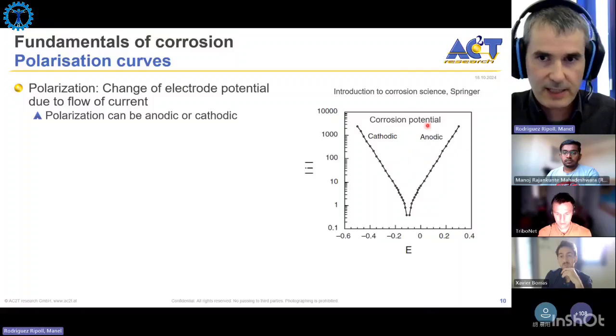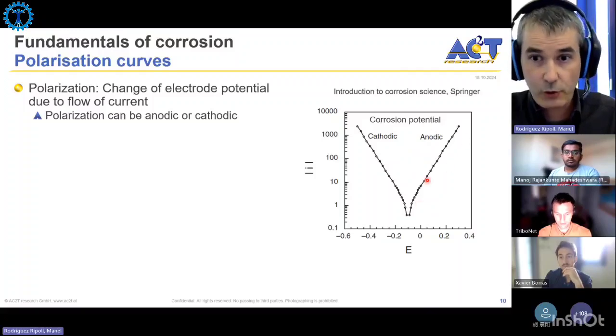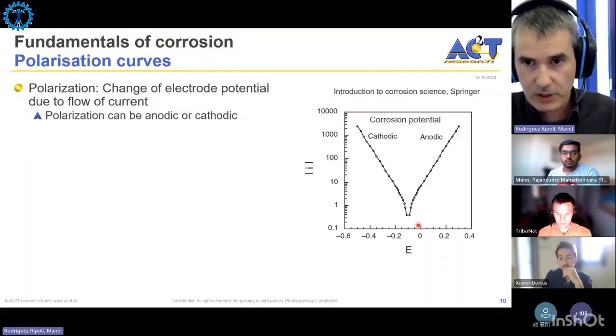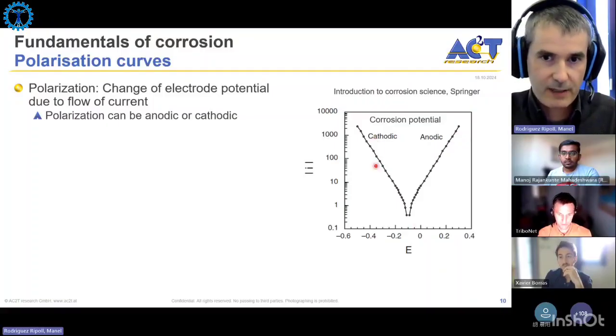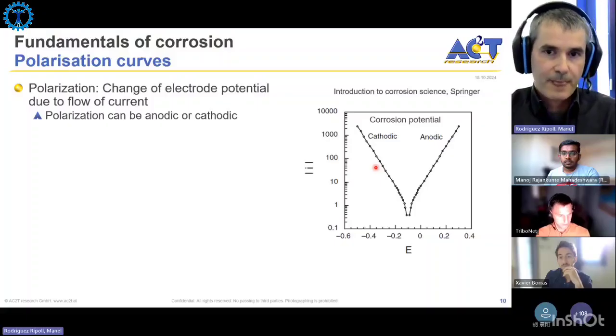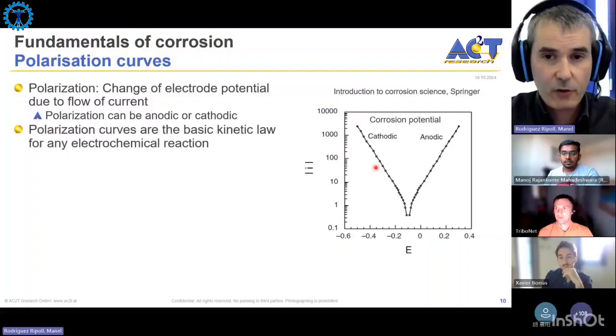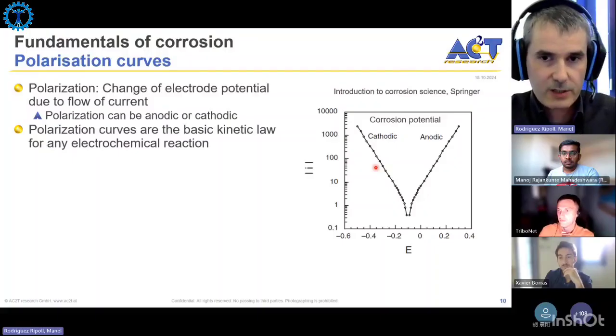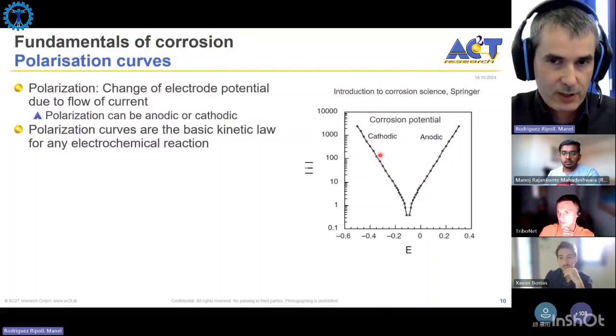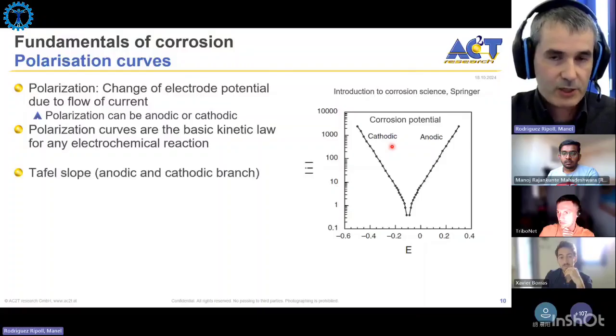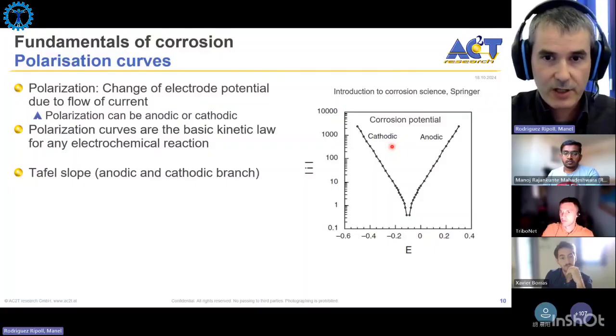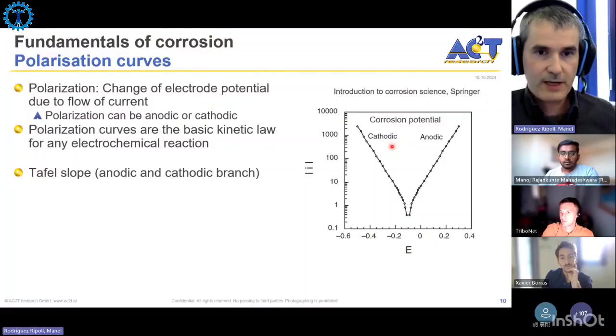It means that here in the anodic range, we are increasing the corrosion as we increase the potential, but in the cathodic domain, the current increase is not due to an increase of corrosion, but to an increase of the cathodic reaction, so that basically we are protecting the material against corrosion. And the polarization curves give us also the kinetics of an electrochemical reaction, so we can take what are called the Tafel slopes.